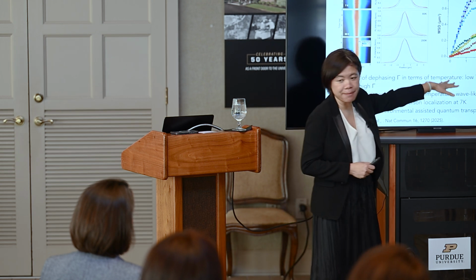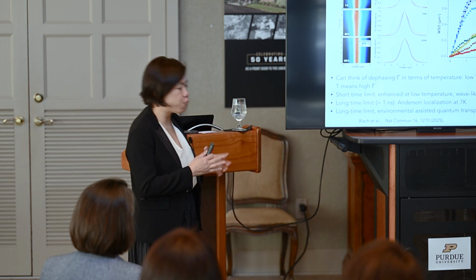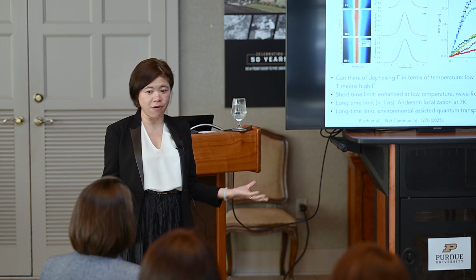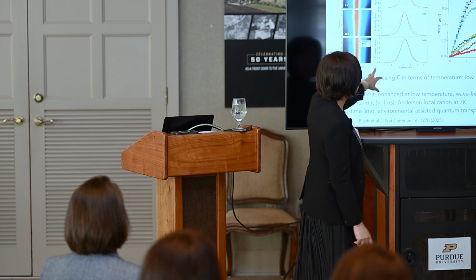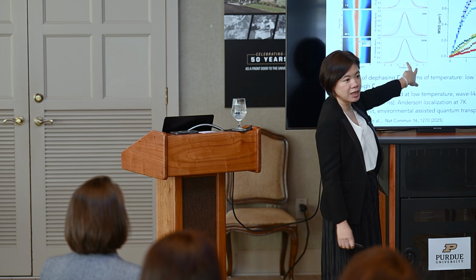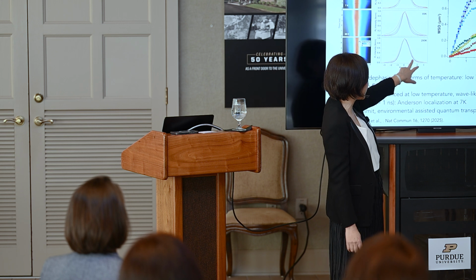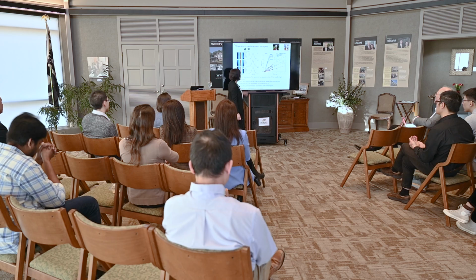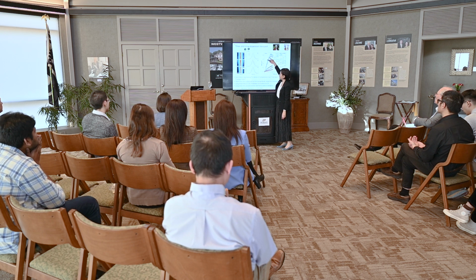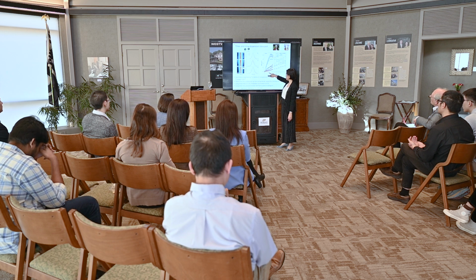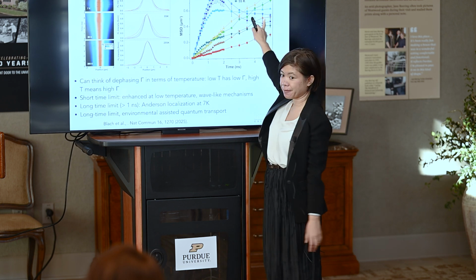And now we're going to look at different temperatures, because we're going to see how this wave-like property of exciton can survive. This is just a one-dimensional slice of what I showed you before, the distribution of the exciton as a function of temperature. Let's start from the very low temperature, 7 Kelvin. Again, the slope of this slide tells us how fast this exciton can move. At 7 Kelvin, this exciton can propagate very, very fast. But then at some point, about a nanosecond later, everything stopped.